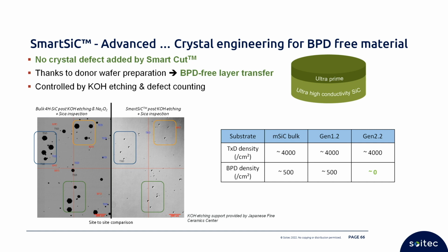So now we prepare, we improve the donor wafers, we generate a BPD-free layer on the donor wafer, and we can transfer this BPD-free layer. And so it means that on the so-called Gen 2.2 SmartSiC Advanced, we do not change the density of dislocations, but for the BPD, basal plane dislocations, which have a significant impact on the device reliability, we are at 0.